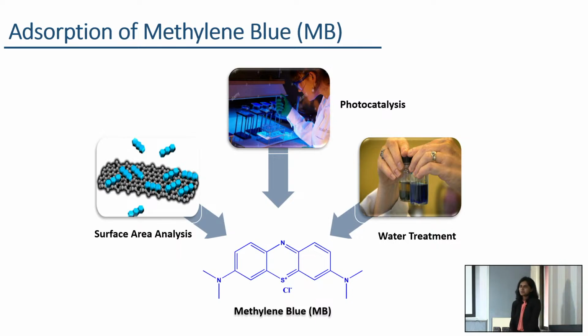After that, the structural variation of these synthesized graphene oxide and reduced graphene oxide samples was probed using the methylene blue adsorption method. Methylene blue adsorption onto GO based materials has been widely used to remove the methylene blue dye from effluent, as well as to measure the surface area and photocatalytic activity of these GO based materials.